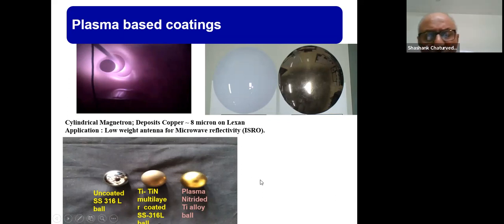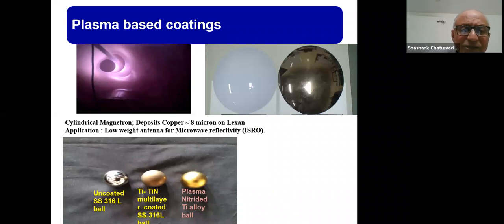There's another application of plasma coatings in the biomedical field. You know that you have this ball and socket joint at the hip, and sometimes people have accidents and damage it. The ball has to be replaced. The earlier standard way was to use SS316L or something, but they tend to get corroded very fast when you put them inside body fluids. Using plasma coatings, you can make multi-layer coatings of titanium and titanium nitride or something else. That tends to increase the lifetime. It makes it more corrosion resistant.